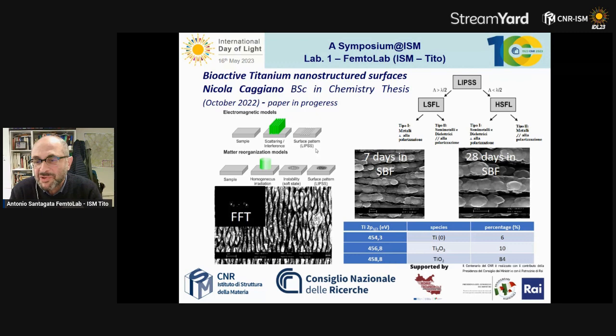About the laser-induced periodic surface structures, we obtain by femtosecond laser impinging on the surface of materials different nanostructures which are formed by ripples, and by fast Fourier transform, we can get the spatial periodicity of our nanostructures. And in terms of properties, even the composition can help us for different application. In this case, we have seen that simulated body fluid can grow some calcium phosphate species because of the composition and periodicity of our nanostructures.